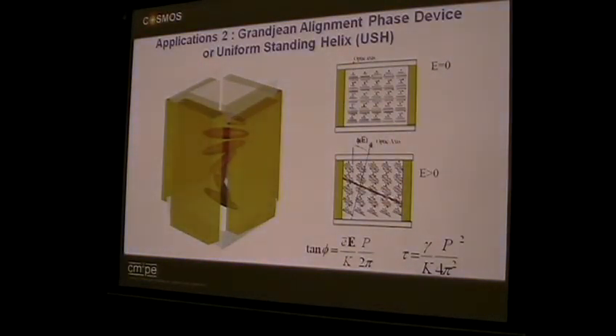What I said was if you apply a field across the helix, you get a rotation of the optic axis. So if I start here with a uniform standing helix, a Grandjean texture, where the liquid crystals are parallel to the substrates, so that's your classical cholesteric, but I'm applying an in-plane field, then as you apply the voltage, the helix tilts over. That's the flexo-electro-optic effect, switching through this angle phi or theta, as we call it. Now what I wanted to do in this particular device was put a field across these two electrodes, then these two electrodes, there's four electrodes there, and what happens is the molecules tilt and rotate. So you can make a phase rotator if you just sequence the voltage you apply across the cell, spin it round, and the tilted helix spins around. And that we use for a telecommunications so-called phase compensator.